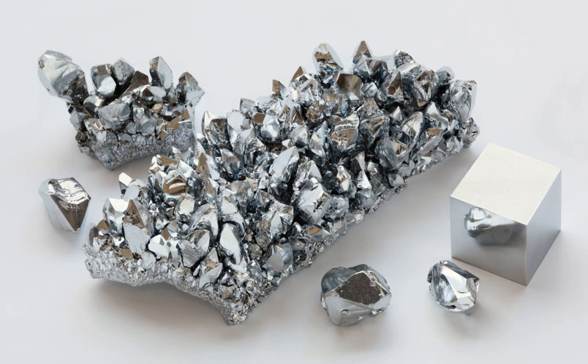4 FeCr2O4 + 8 Na2CO3 + 7 O2 → 8 Na2CrO4 + 2 Fe2O3 + 8 CO2. 2 Na2CrO4 + H2SO4 → Na2Cr2O7 + Na2SO4 + H2O. The dichromate is converted to the chromium(III) oxide by reduction with carbon and then reduced in an aluminothermic reaction to chromium. Na2Cr2O7 + 2 C → Cr2O3 + Na2CO3 + CO. Cr2O3 + 2 Al → Al2O3 + 2 Cr.